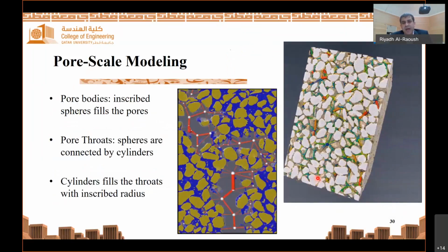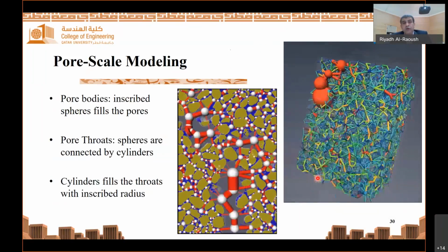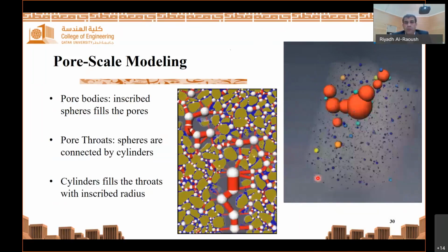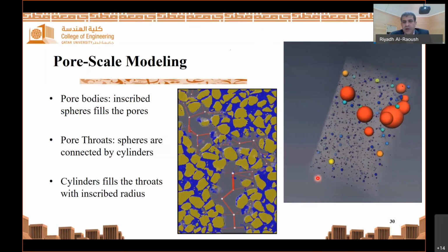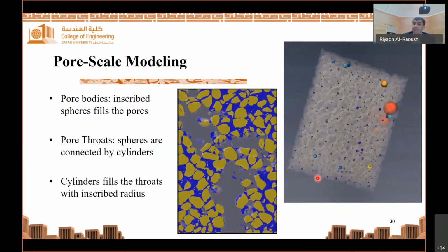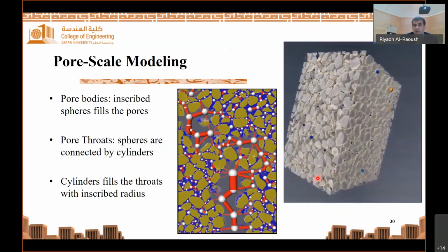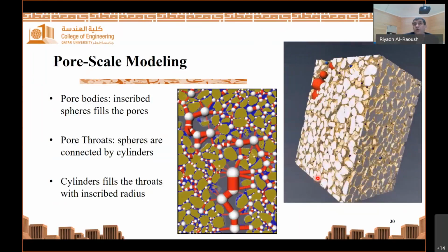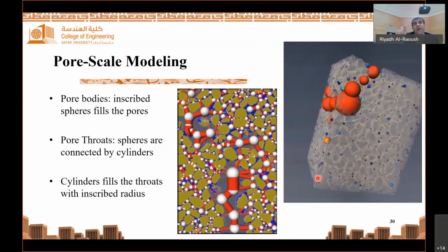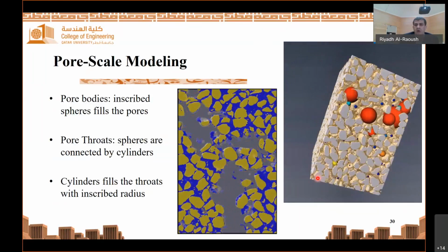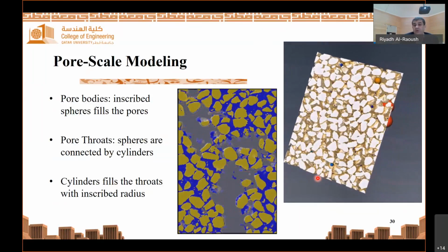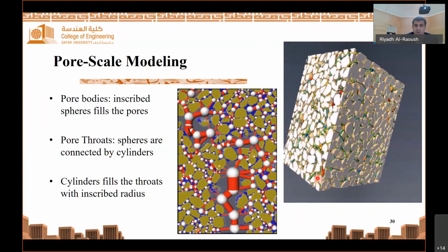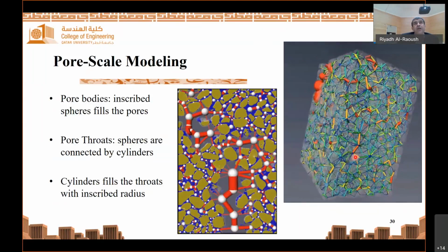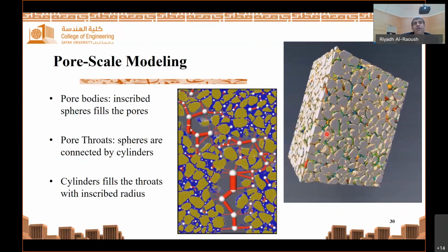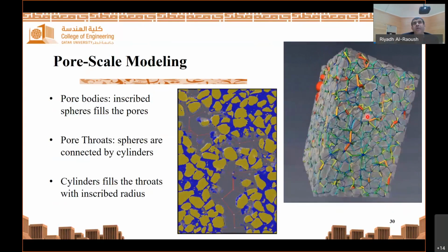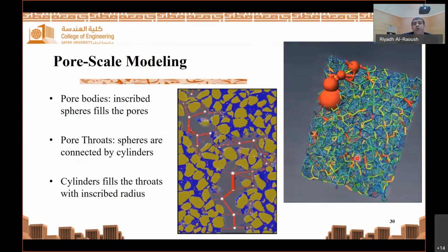Here you see the simplification of the complex pore geometry to the pore network structure, which is the base for pore network modeling. This pore network structure is used for pore network modeling based on the physics of the relevant problem of interest. You can see that this is a simplification of the void space, in other words, pore bodies connected by pore throats. There are many algorithms available to obtain the distribution of pore bodies and pore throats. In this image here, these are the pore bodies and these cylinders are the pore throats. So we can follow the physics of the fluid dynamics in a sample like this one, so we can build predictive models.